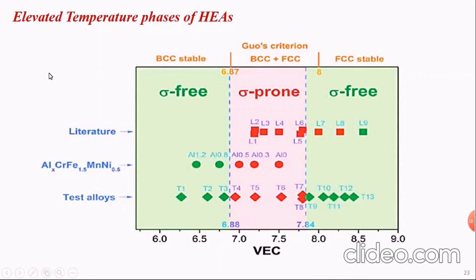Also, in high entropy alloy, you have to pay attention. Similar to the case of steel, we have high temperature phases which are brittle and detrimental to the mechanical properties. In this area of valence electron, we have sigma phase. Sigma is a brittle phase, like in steel. But in this range of valence electron, we don't have sigma. So you have to consider which application you desire to use. Do we use high entropy alloy at lower temperature or at higher temperature? If you are going to use it at higher temperature, you must check your total valence electron and see if your alloy is subjected to sigma phase at high temperature or not.